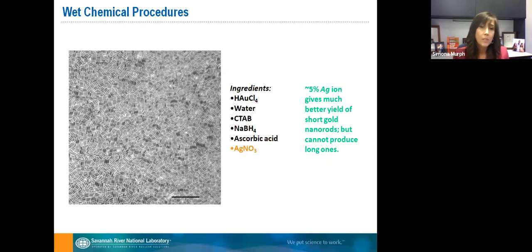We can grow these rods up to 100 nanometers in length, and we can tune their length. I will tell you in a second why we are really interested in tuning the length of these nanorods. Everything is really important in this reaction, where we have these ingredients and the steps that we are using. But the presence of this additive ion, the silver ions, allows us to tune the length of the nanorod.